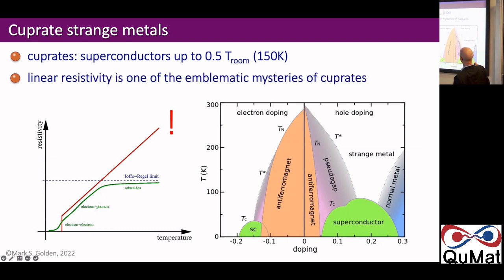So this linear resistivity is one of the emblematic mysteries of the cuprates, and this gives rise to a phase diagram. If we think about the hole doped cuprates, on the left-hand side you have antiferromagnetism, which you can understand in the Hubbard model because of the strong correlations. Then you have a superconductor, which we don't yet understand. And of course, the superconductor is the child of a parent, which is a metal. When we're cooling it down, there's a pairing instability, and the metal is less energetically favorable than the superconductor.